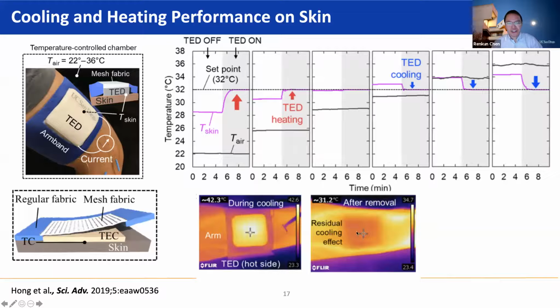And this infrared image really shows when the device is cooling, the outside temperature, the hot side of the device, actually is hot to dissipate the heat to the environment. And the hot side temperature is as high as 42 degrees Celsius. So you can dissipate heat from 42 degrees Celsius on the hot side to 36 degrees Celsius in the air. So when someone actually wears this device, they will feel cold, but probably you don't want to touch them because they're actually hot on the surface.